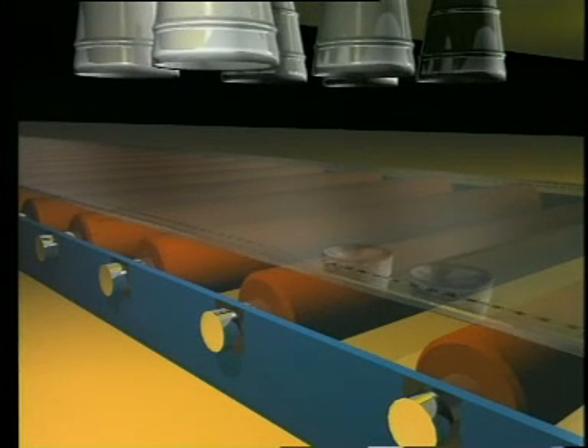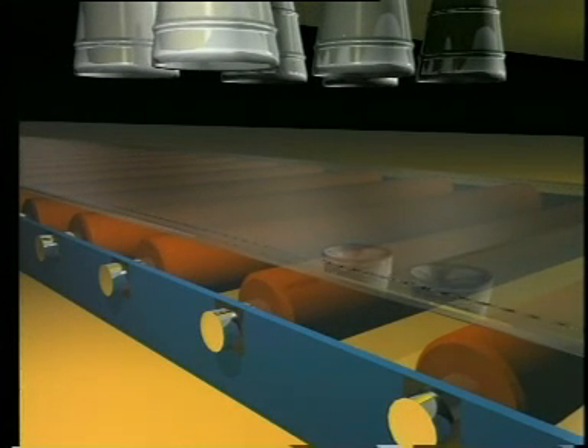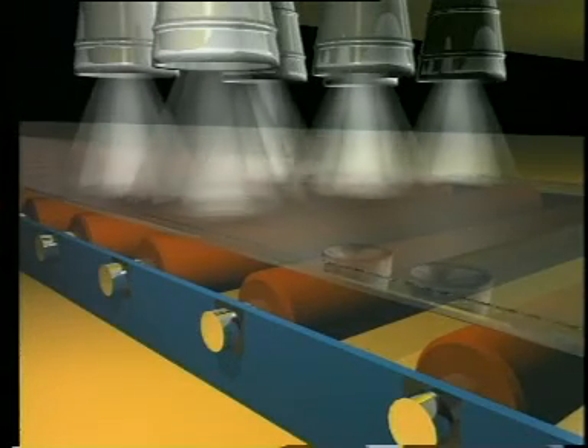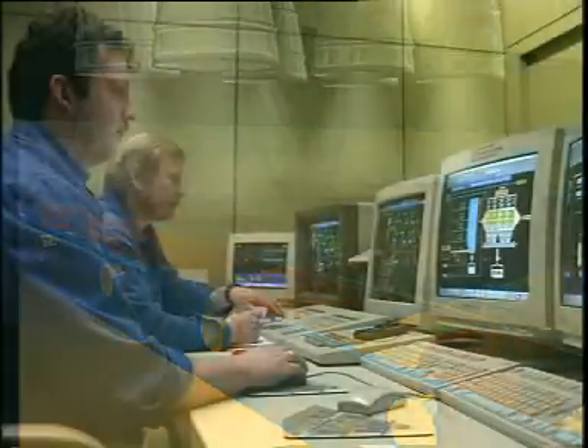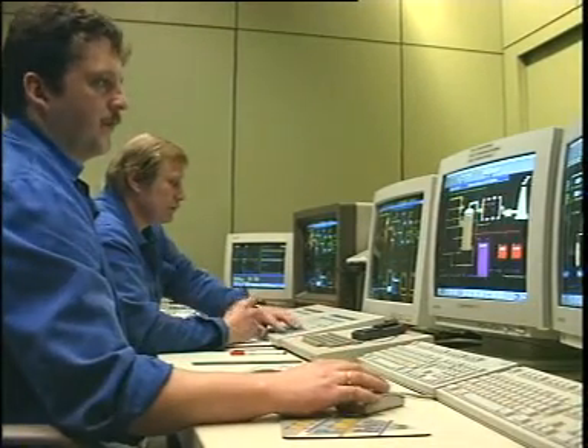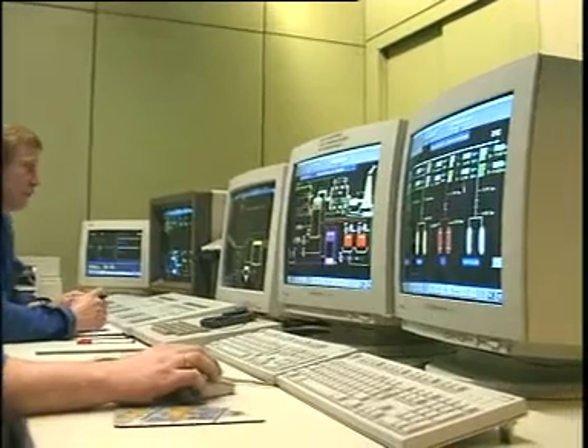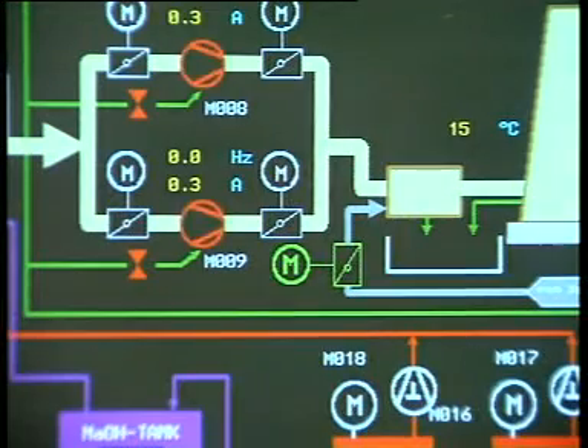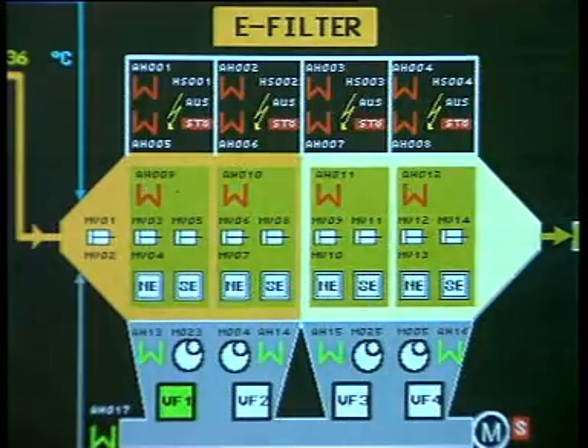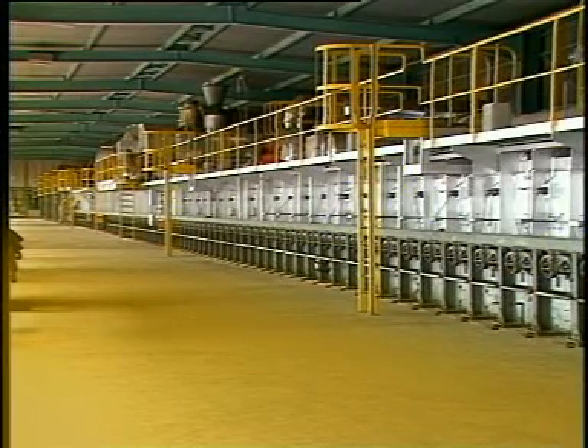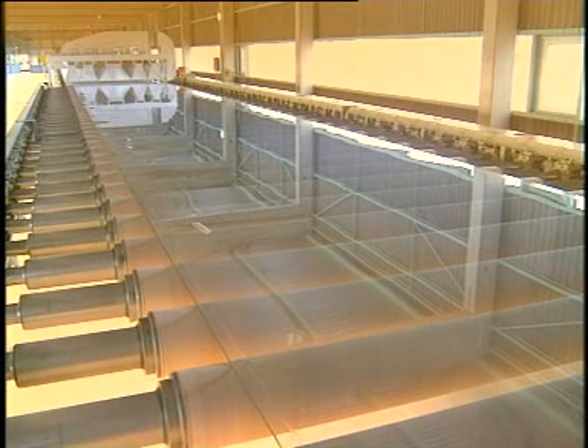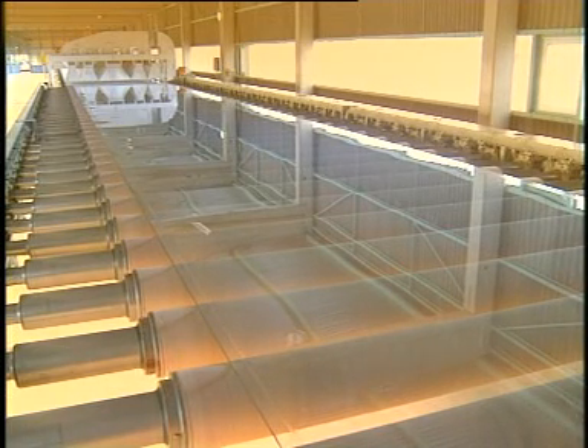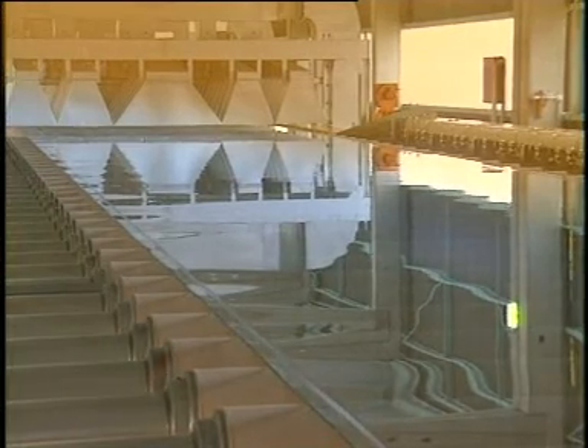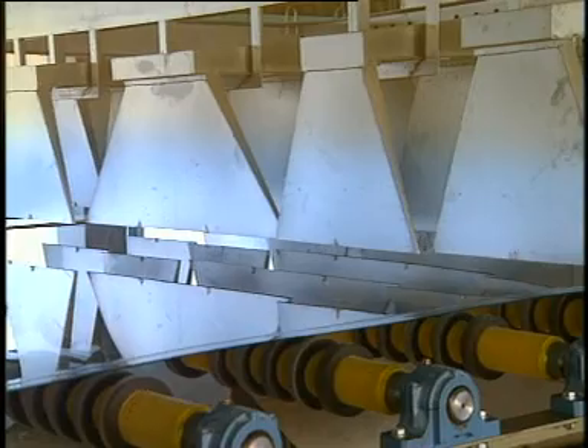Special properties, including the ability to reflect heat, can be imparted by applying an extremely thin metallic layer to the glass while it's still hot. Pilkington K-glass, produced in this way, increases the efficiency of double glazing by as much as 50%. The glass now enters the annealing lehr, where any stresses are removed by a controlled cooling process. In a length of 250 meters, the glass is taken from 600 degrees centigrade down to room temperature. At this stage, the glass is perfect. Only the indentations left by the top rollers remain to be scored, ready for removal.